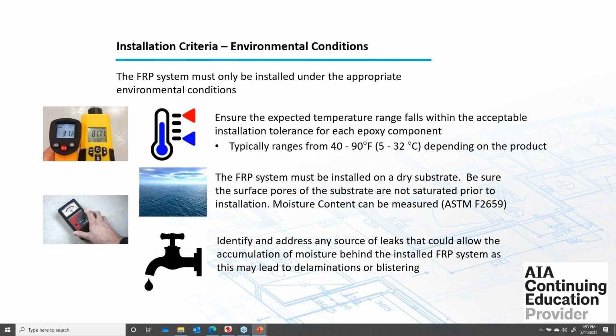Second, the FRP system must be installed on a dry substrate. So be sure that the surface pores of the substrate are not saturated with water or moisture prior to installation. For that, you can measure the moisture content using ASTM F2659. If the result is under 4%, you're good to go. If it's above 4%, you have to consult the manufacturer or try to work something out with the engineer of record to fix that.